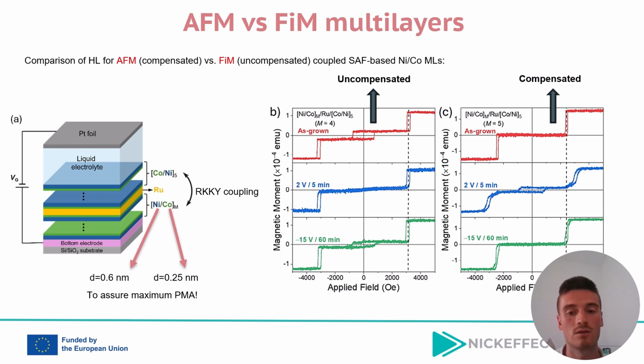To ensure a strong perpendicular magnetic anisotropy, the nickel-cobalt layer thicknesses were optimized, as we can see, to 0.6 nanometer and 0.25 nanometer each layer, respectively. The magnetic hysteresis loops recorded, shown in figures B and C, show the evolution of magnetic moment versus applied field for different voltage treatments.